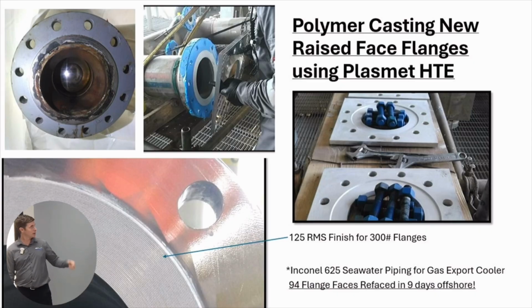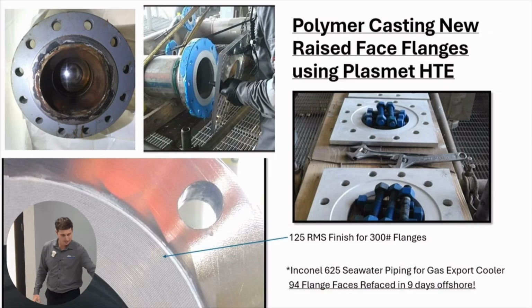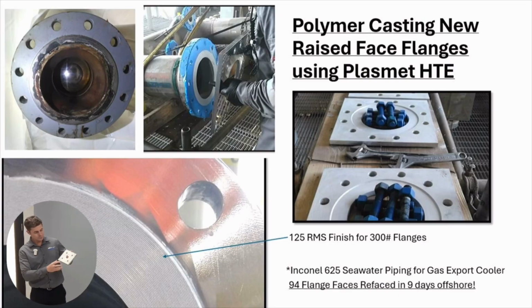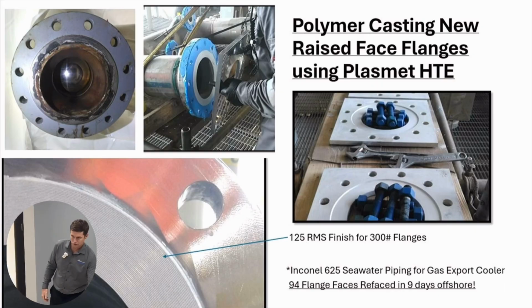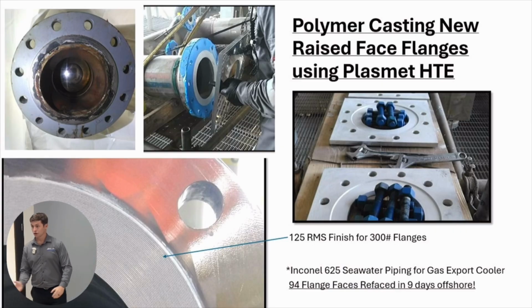This is a project that I went out to help out with this summer in the Gulf of America. This is something where we used a casting method. I brought the 1.5 inch because it was easier to fit in the bag, where we fabricate with our machine shop, and Qualitech can do the same, flange formers to spec. So this is a 300-pound flange, raised face, with 125 RMS finish. We sent a crew offshore with coating, the Plasmet HTE coating.